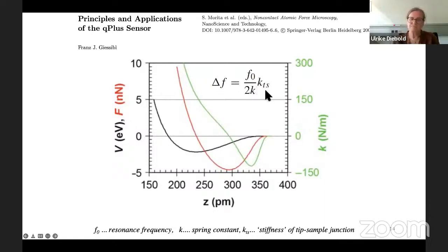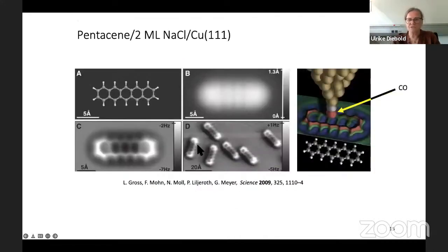And then we can measure the change in resonance frequency as the tip goes in and out, approaches the surface and comes back, and then integrate that and get the force. So this gives really wonderful images. There's a very famous one of a molecule on the surface. This is a non-contact AFM image. You only get that when you have the tip under real, atomic control. So in this case, it's functionalized with one carbon monoxide molecule.